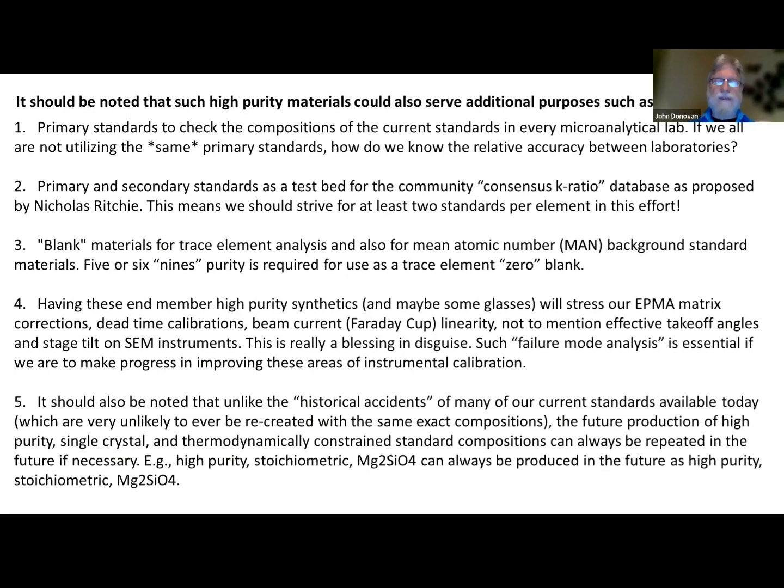And consider this: these end member synthetics, Mg2SiO4, Fe2SiO4, CaMgSiO3, whatever these synthetic minerals are, are going to test our matrix corrections. When I've done these tests, the matrix corrections work great, but there are always cases where something we didn't know shows up, and this is the way we discover it. So having these high accuracy synthetic materials is going to be great for testing our matrix corrections.